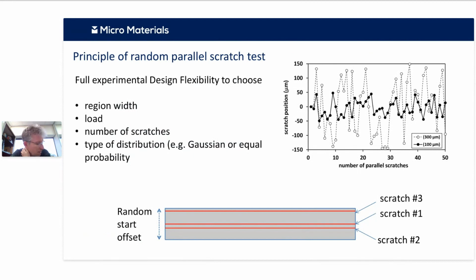So why this is important essentially is, John Williams showed years and years ago that if you're scratching something and it's a perfectly smooth sample, then typically you're going to get ploughing or something like that. But when you've got some surface roughness, then you get transition to more severe wear modes like cutting and abrasion. So what's happening here is that the damage from one scratch, or the pile up even from one scratch, is affecting the next scratch nearby, and this is leading to transitions in mechanism.